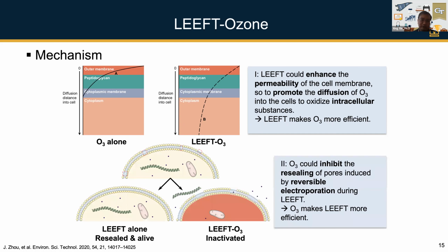Another way to explain this: when we do the LEEFT itself, some of the membranes get reversible damage. You have a cell, you have electroporation happen, so you have pores form on the cell membrane. If you don't have a post-LEEFT ozone process, these pores will be able to recover, they will reseal, and then the cells will be fine. But in this case, we combine LEEFT with ozone, and the ozonation prevents the recovery of the cells. So this is a very synergistic combination of LEEFT and ozone.